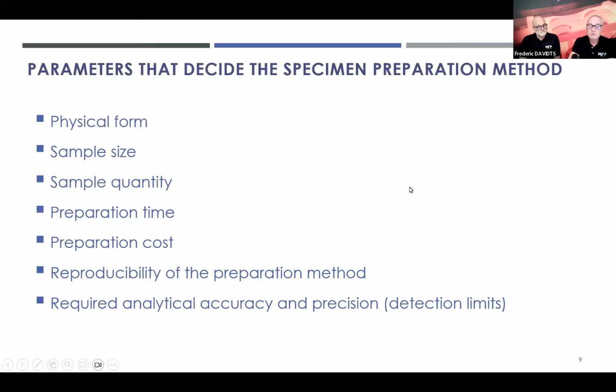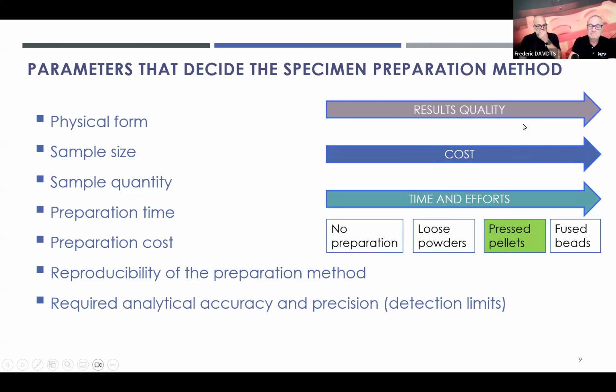And when we talk about precision, we also talk about detection limits. We have seen in our former webinar, where we spoke about fused beads, that results quality is really good, but that the cost, time and effort are somehow higher than when we prepare a pressed pellet. So their cost and time is somehow reduced, and the results quality is still very good, but maybe, at least for major elements, it can be less good than for fused beads. But we will see that for pressed pellets, we will have better results for certain trace elements. So detection limits will be better.